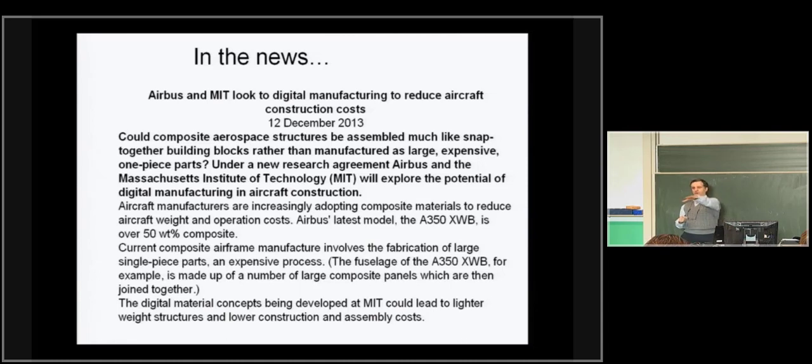In fact, the reasons are more what the front here said. But raw material is usually about 12% of the total cost. So if the raw material is 10 times more, still you are paying more for the final product. The steps in the process and the complexity of having to make a part that's not flat anymore add a lot to the cost. So composite manufacturing is expensive, and there's one aspect of the manufacturing process, the assembly.